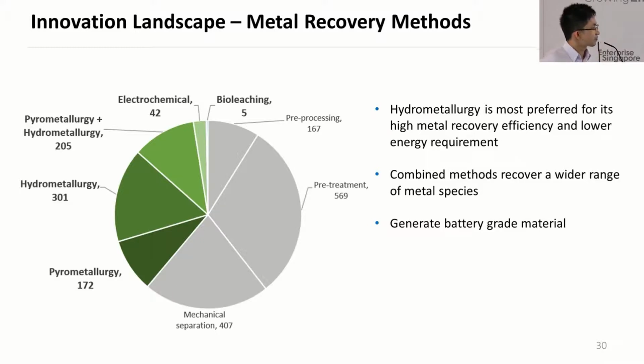So you find that hydrometallurgy is the most preferred method for its high metal recovery efficiency, and it also has lower energy requirements. As per our study, we have also uncovered that a combination of pyro and hydro methods is rather preferred because we assess that it will recover a wider range of metal species, which I'll explain in a little bit more detail in my subsequent slides. So the key here is to generate battery-grade material from these processes so that they can fetch a higher value in the market.